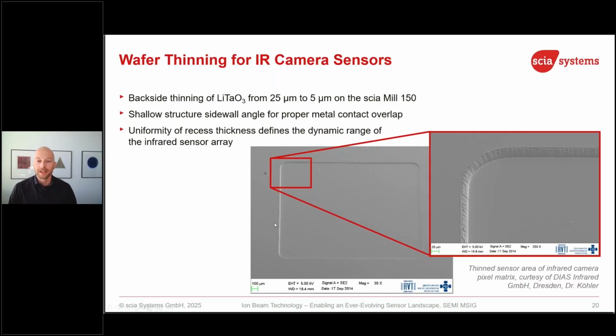And if this would be a 90 degree sidewall, and you evaporate or sputter some metal on top, then maybe you don't have electrical contact. That's why a certain angle is needed here. And lithium tantalate, you can't etch it with RIE, that's why ion beam etching is used.